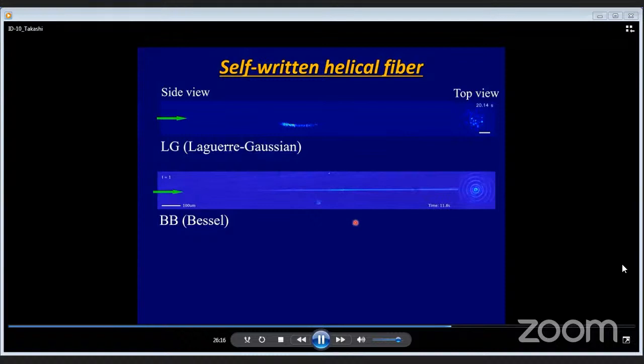In the case of the Bessel beam, laser beam comes into the cell. Fiber is created. And the spatial form is always multiple ring. And you can find this multiple ring is rotated in clockwise direction. This rotation of the transmitted light means fiber is twisted. The good evidence of the helical fiber formation inside the resin. And this is quite important. Even after fabrication of the fiber, transmitted light is still multiple ring, namely the Bessel beam can propagate inside the fiber safely. Effective length of the fiber reaches up to 1 centimeter.